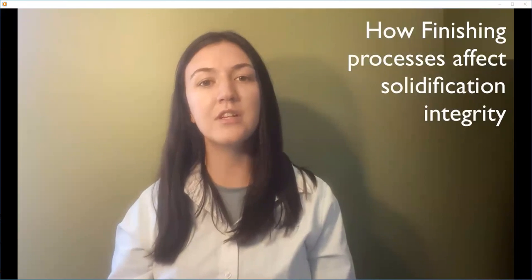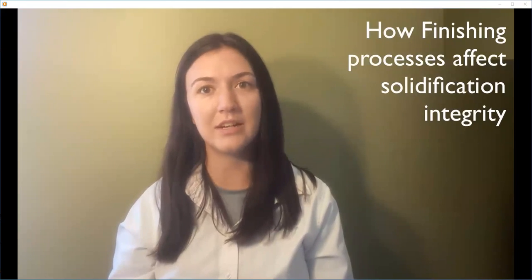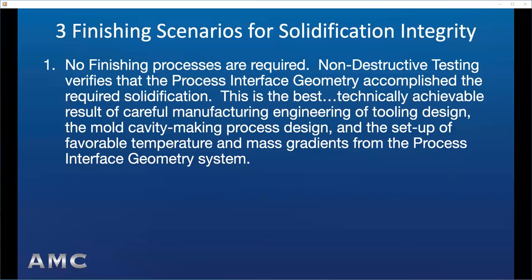Moving on now from protecting as-cast surfaces, let's look at how finishing processes affect solidification integrity. There are 3 finishing scenarios for a high specification casting, requiring verification of specified surface and/or internal integrity. So first, no finishing processes are required. Only non-destructive testing verification that the casting's design geometry and the metal caster's process interface geometry, that is the gating, risering, venting, and chilling, accomplished the required solidification integrity as the liquid alloy cooled in the mold.